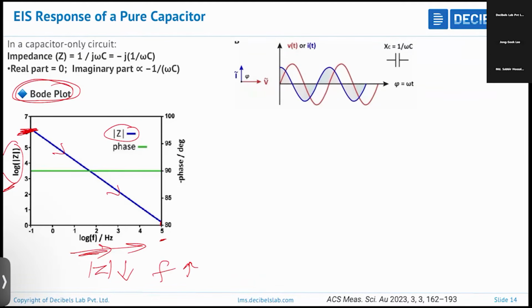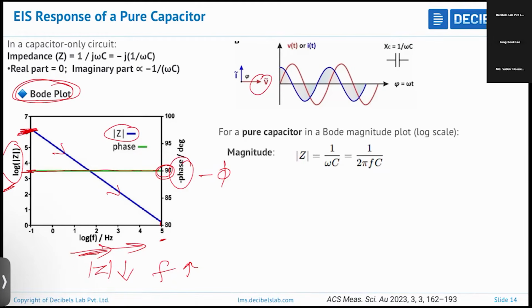This clearly indicates that if you record a Nyquist or Bode plot of any electrochemical system and it appears like this, then it has only a capacitor. And you can see that the phase change is about -90 degrees. The voltage is delayed by 90 degrees. That's why it is constant. So the phase change is constant in a capacitor.